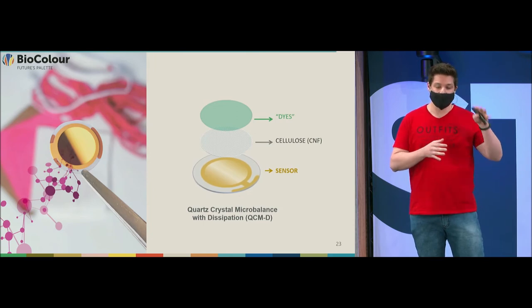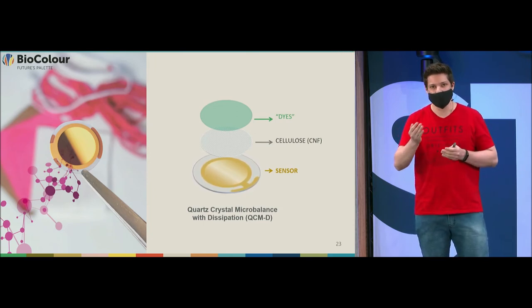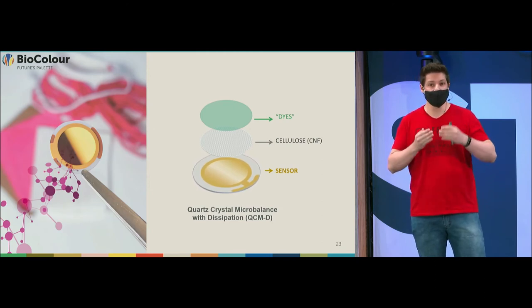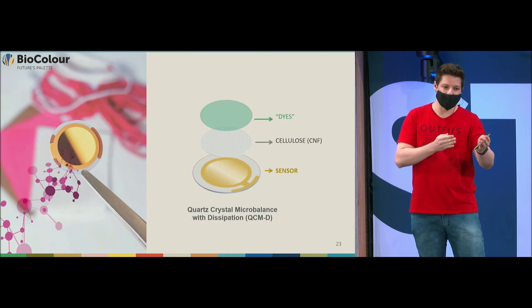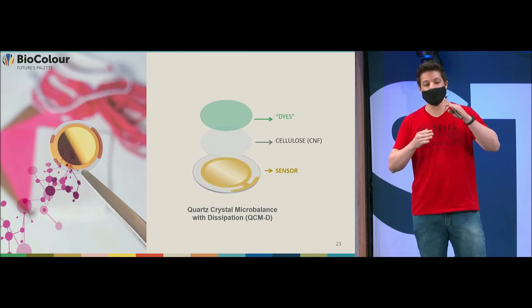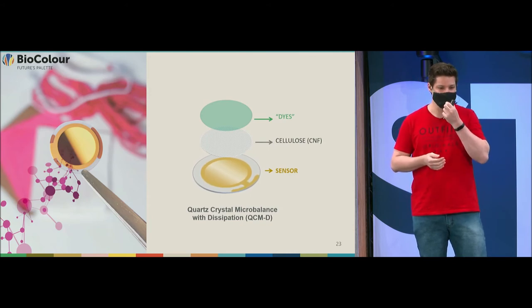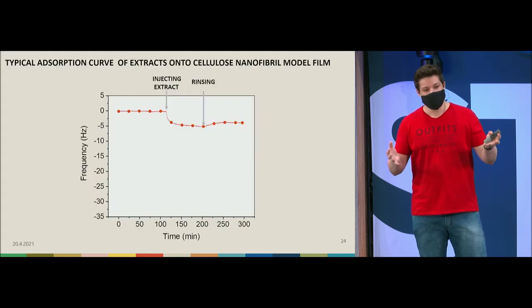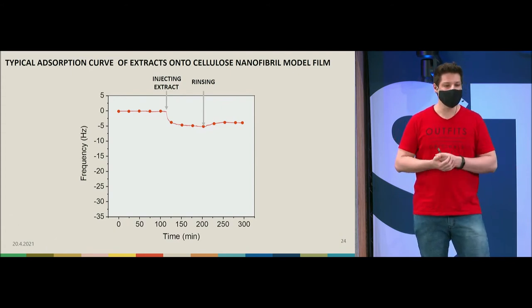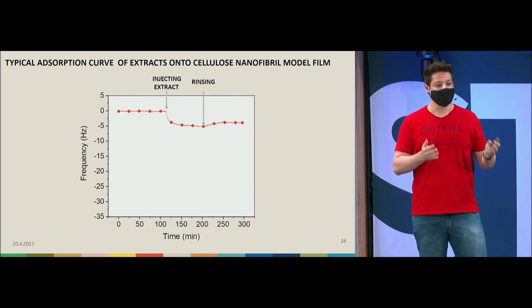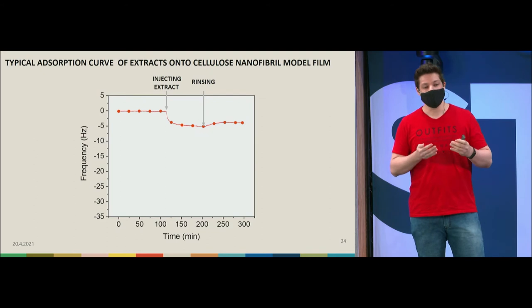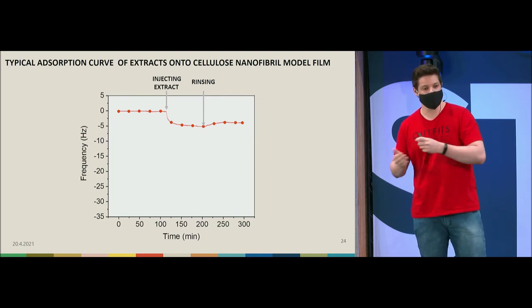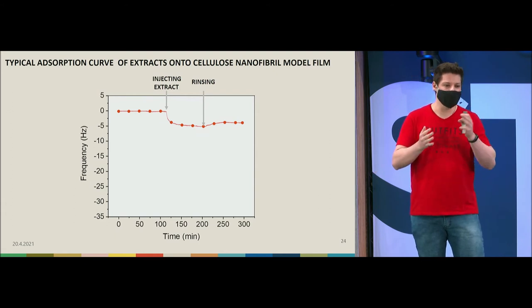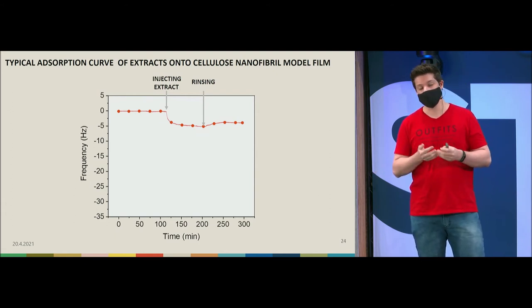And then the sensor has some vibration. And when you put it inside the machine and we inject the dyes, if some dye is absorbed into the cellulose, then the frequency changes, and then we can collect some data from it. So this is the typical curve that we obtain using this technique. I will not go into much detail about it, but I can tell that the change in the frequency has low values. It means that the absorption is not that strong. And when we rinse to simulate the washing of these textiles, part of the material is removed. Here we have more or less 25% of the material that was removed.